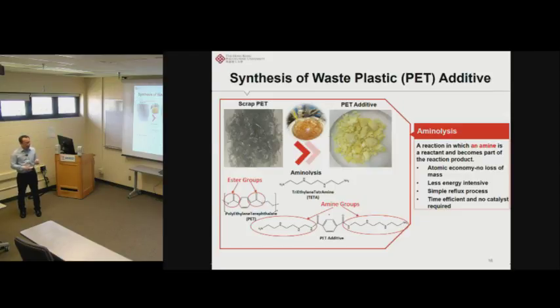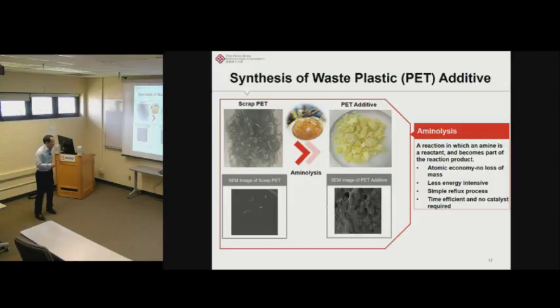And these amine groups, later on I will show, are actually very helpful to improve the performance of the asphalt mixture, especially their fatigue and moisture damage resistance. And this is the change we can see from the SEM image. Before the treatment, you can see the surface of the PET is quite smooth, and afterwards its surface becomes very rough. And such a rough surface also allows very good mixing between the PET additive and the asphalt binder.